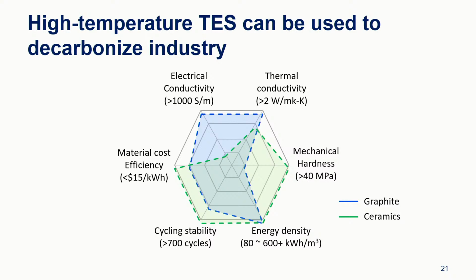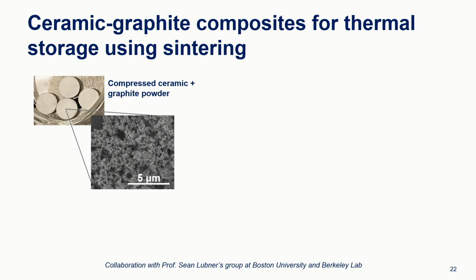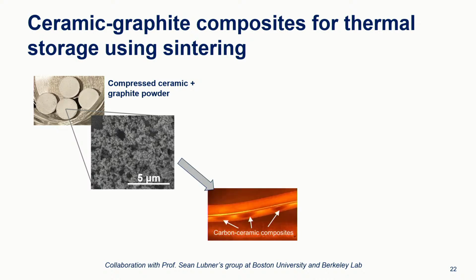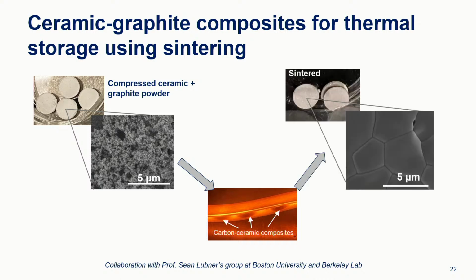And so we've been working with composites, combining the benefits of ceramics and graphite in order to get these desired properties. So this is ceramic powder, just aluminum oxide with graphite, and then we sinter it at about 1,700 degrees Celsius, and this is what the sintered pellet looks like. You can see that we've really densified the grain structure to create these rigid sintered composites.